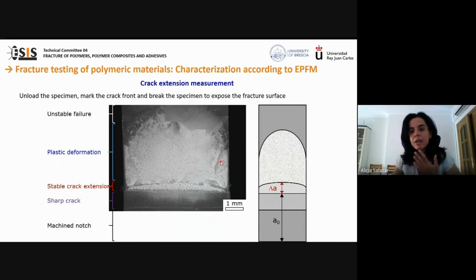For the determination of the JR curves, we also need the measurement of 2 crack lengths. The initial crack length, a0, includes the machine notch and the sharp crack, and the stable crack length extension, delta a. This micrograph shows the fracture surface of a ductile polymer, an ethylene propylene block copolymer, where it is observed the sharp crack, the stable crack extension, here it is, the ductile fracture or the plastic deformation, and then a unstable failure.